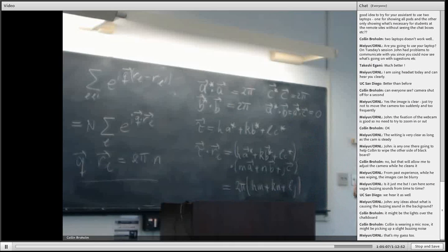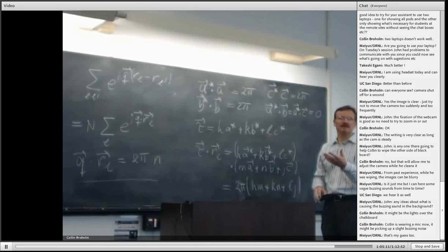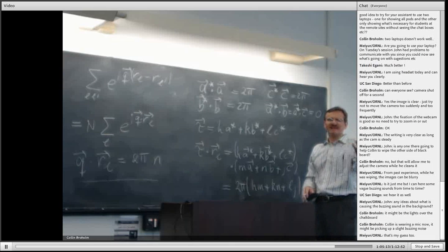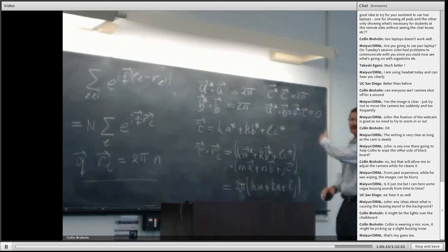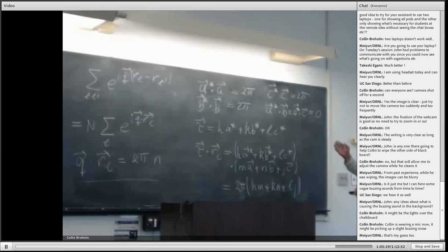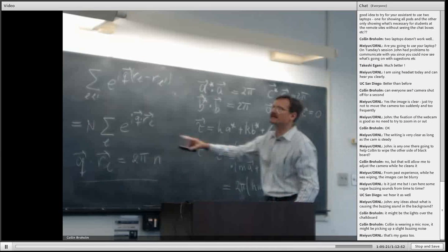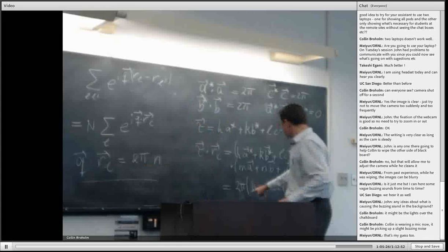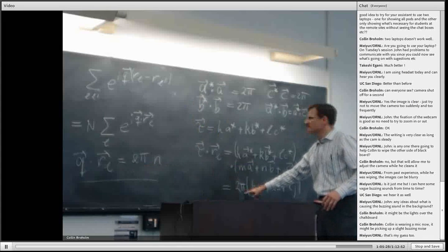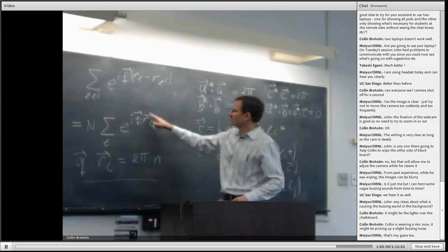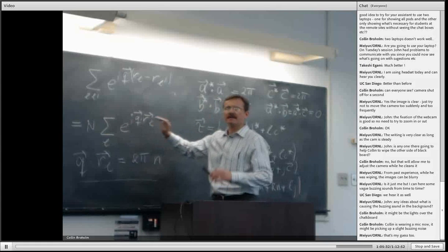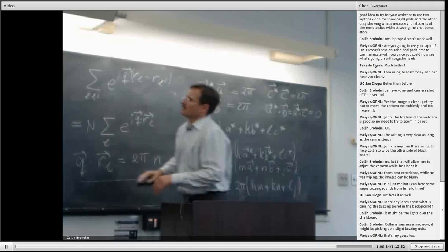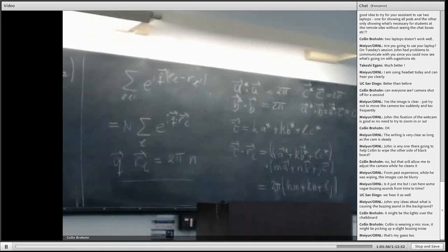I'm sure most of you have seen it, but some of you may not exercise it as much as you do when you're doing scattering. So when we're working with either X-rays or neutrons, this is basically the space that we live in, the reciprocal space. So what happens then for those particular values of Q, as we've shown here, the dot product ends up being equal to 2 pi, and then all of these terms will add on top of each other, and I get a finite value. So now I'm going to double back to this location.